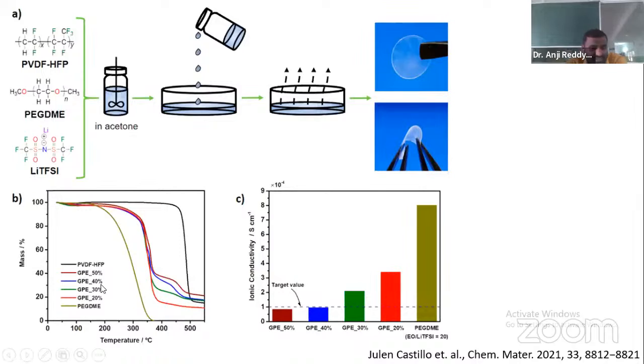Okay. This is the addition of the plasticizer PEG-DME, one of the safest plasticizers. Right? Ionic conductivity. How does the ionic conductivity increase? We can observe the ionic conductivity values on the order of 10 to the power of minus 4. This is without polymer, PEG-DME with the lithium salt. How much did they get? The conductivity is very good. And with different concentrations of PEG-DME with the polymer, how the conductivity changes, this is also very good. This is also 10 to the power of minus 4. The polymer electrolyte film, whatever we are observing here, also has very good conductivity.